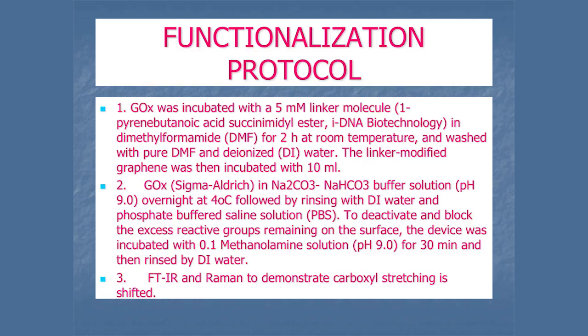Now, the functionalization protocol: you incubate the graphene with a 5 millimolar linker molecule, 1-pyrenebutanoic acid succinimidyl ester, in dimethylformamide for 2 hours at room temperature. Then it is washed with pure DMF and deionized water. The linker-modified graphene was then incubated with 10 ml of glucose oxidase. Now, glucose oxidase was originally obtained from the fungus. We can commercially buy it, but you have to purify it extensively. Protein purification is an art. There is nothing called 100% pure protein. You can call it 99% plus.